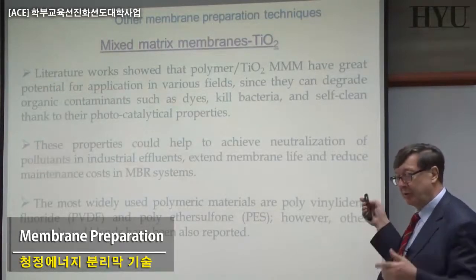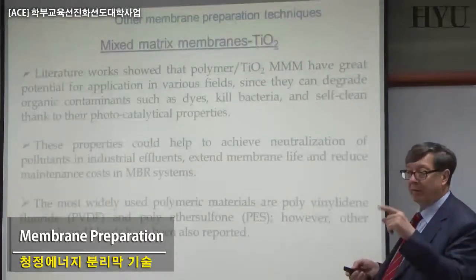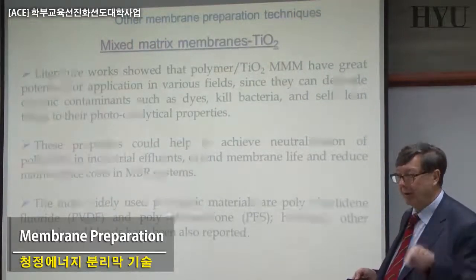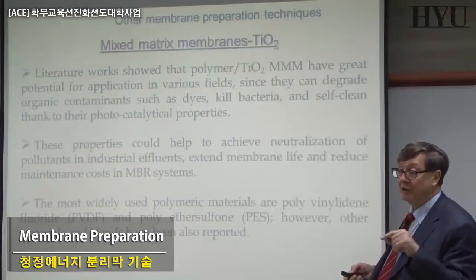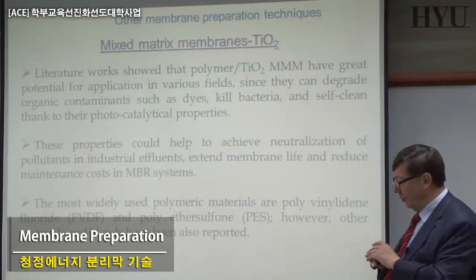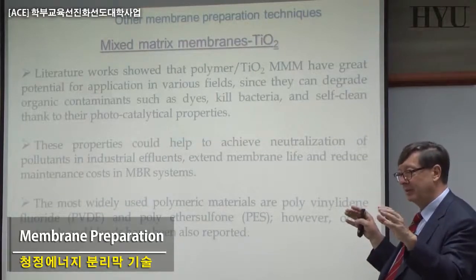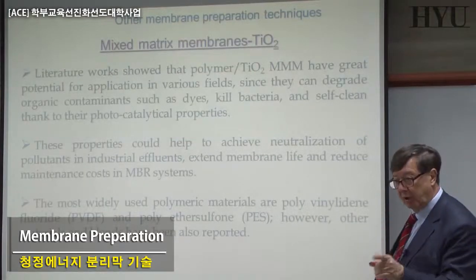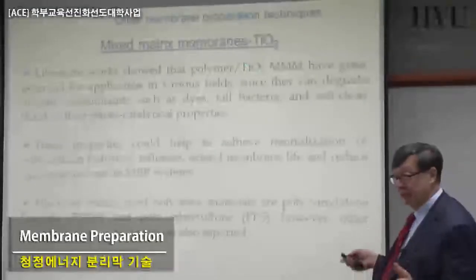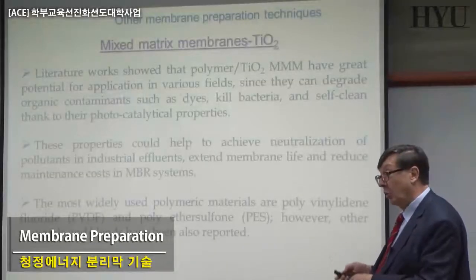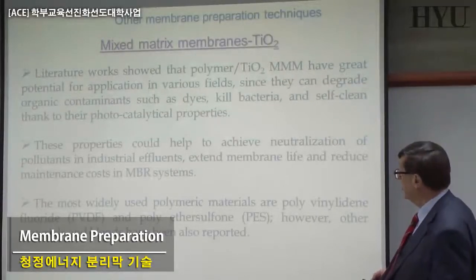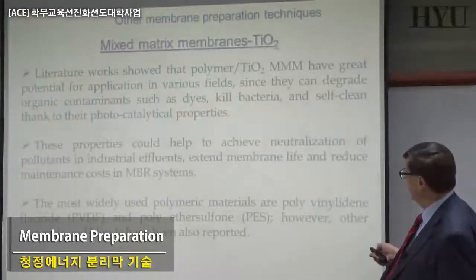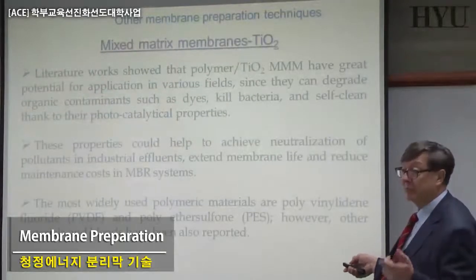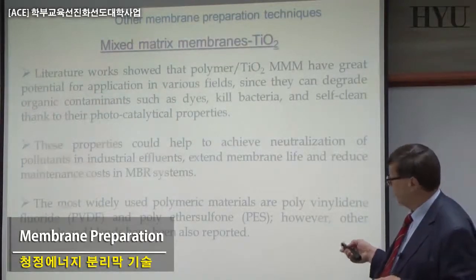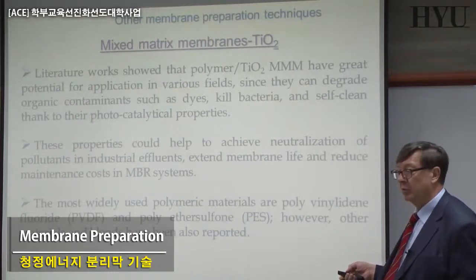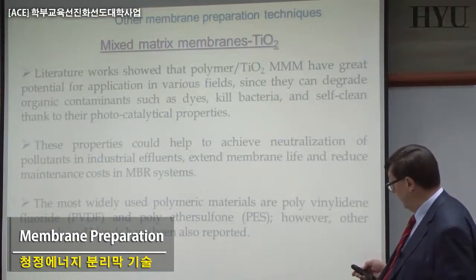For example, I'll show you an example in which we were working on polyoxometalate. We added some fluorine compound, a complicated one, but fluorine, and what was before a bad cluster became a very nice homogeneous distribution. If you do this and you're able to do it with titanium, etc., these are quite interesting improvements. That's what people are trying to do today. And so you can have a way to metabolize, for example, phenol. Titanium dioxide is quite interesting to destroy phenol, which is difficult to remove in other ways, and that can be one of the ways of doing it.